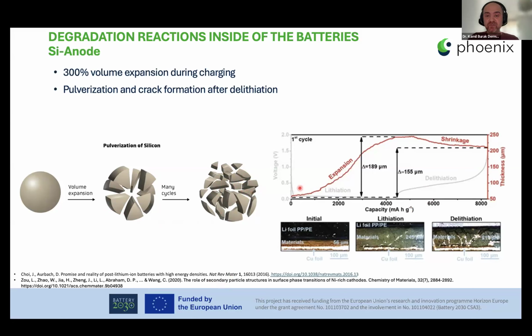As you can see from the first cycle, the expansion is rather high during charging, and during discharging the shrinkage is rather slow, leading to a huge amount of change in thickness according to the dilatometry results. The images below show how crucial it could be. In the initial phase, the stack seems all in order, but after lithiation and delithiation, you will see quite huge and dramatic cracks in the electrodes.